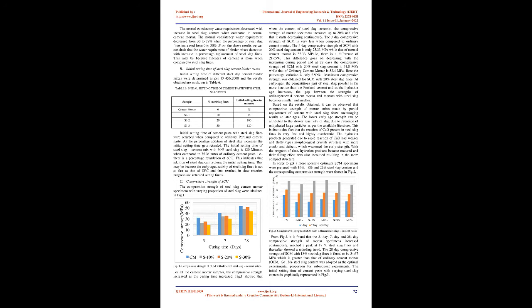B. Initial setting time of steel slag cement binder mixes. Initial setting time of different steel slag cement binder mixes was determined as per IS 456:2000 and the results obtained are shown in Table 6. Initial setting time of cement paste with steel slag fines was retarded when compared to ordinary Portland cement paste. As the percentage addition of steel slag increases, the initial setting time gets retarded. The initial setting time of steel slag cement mix with 30% steel slag is 120 minutes when compared to 75 minutes of ordinary cement paste, i.e., there is a percentage retardation of 60%. This indicates that addition of steel slag can prolong the initial setting time. This may be because the early age activity of steel slag fines is not as fast as that of OPC and thus resulted in slow reaction progress and retarded setting times.